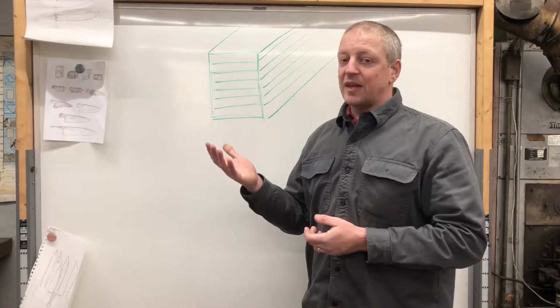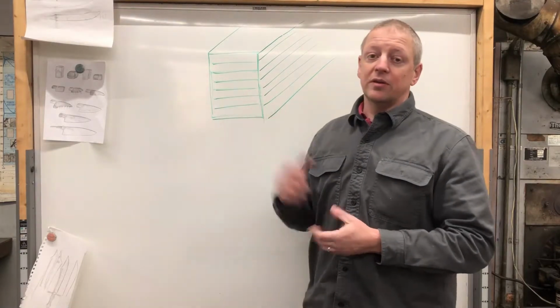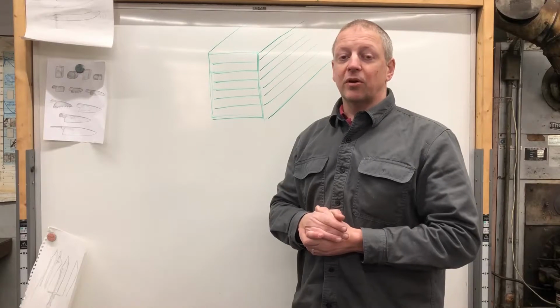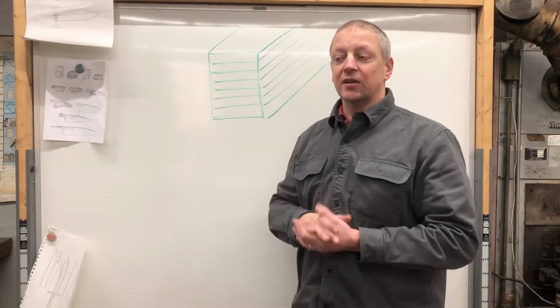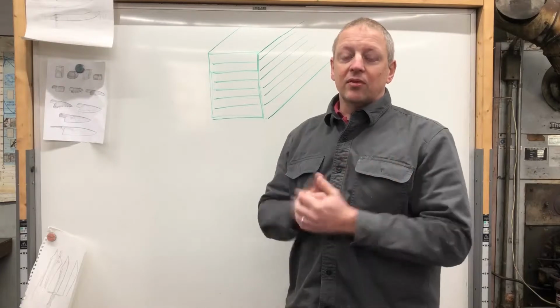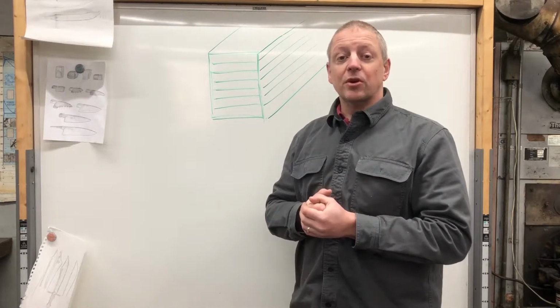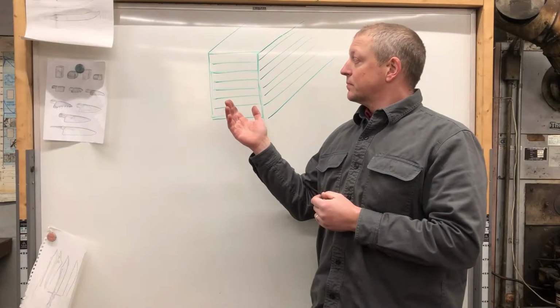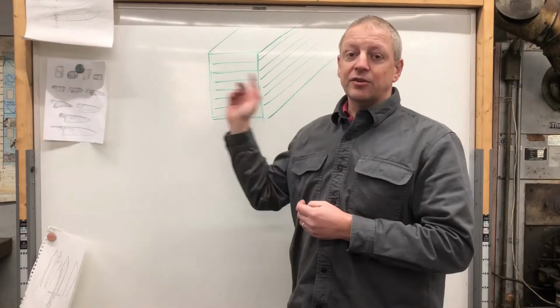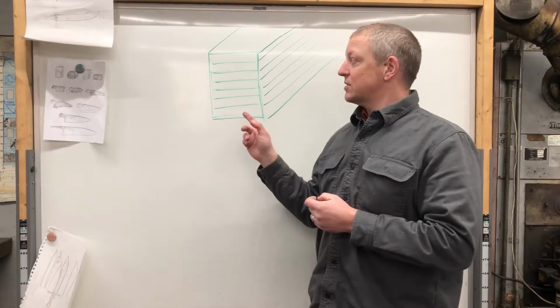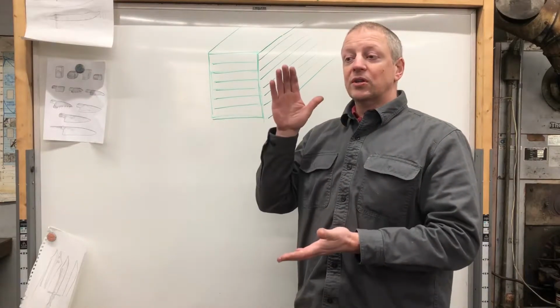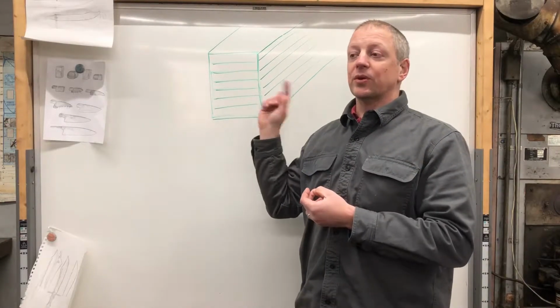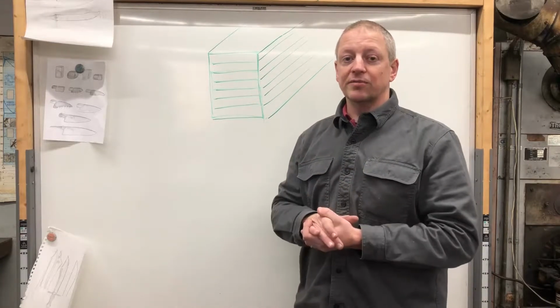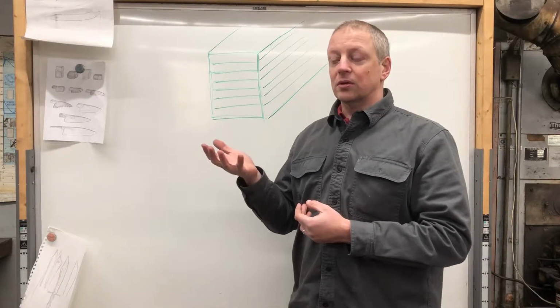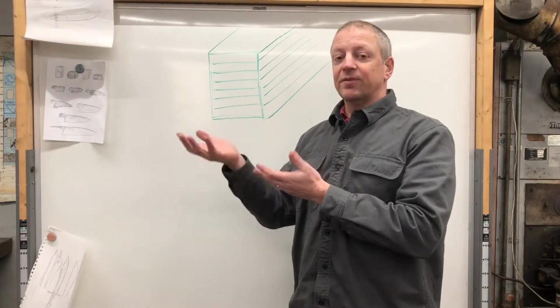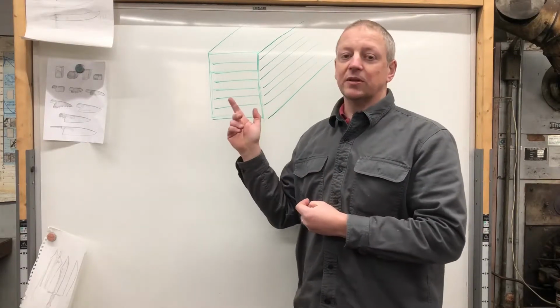The downside of doing this is, one, you've fluxed your billet, so you've also fluxed the inside of your forge. As all of us know, flux and forges don't get along well. And also, now you have introduced flux into the equation. It means that when you go to restack, you want to make sure you've absolutely cleaned all your surfaces. You don't want that old compound of flux and iron oxide between your layers.